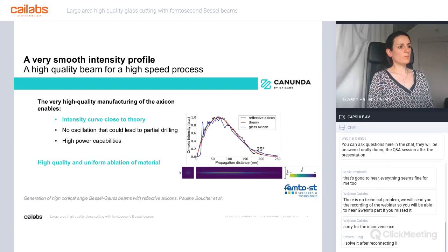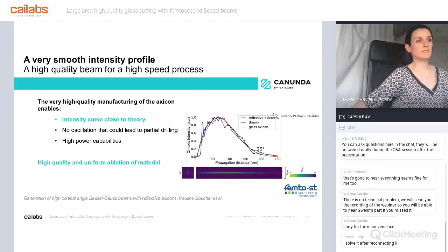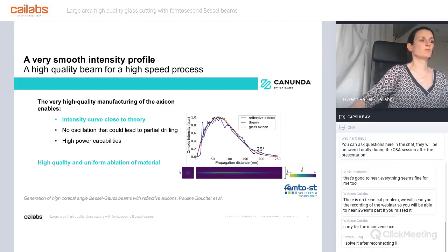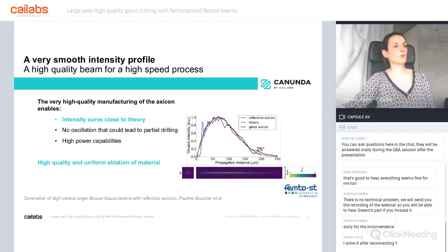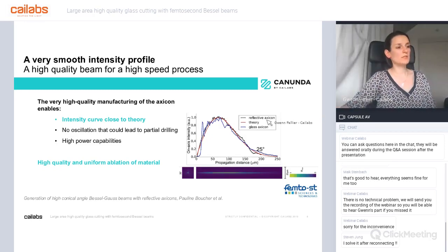The Bessel beams that we have generated with reflective AXICONs are actually the Bessel beams with the best quality that we have found in the literature. You can see that first on this slide: in red you have the theoretical curve of a Bessel beam, and in black you have what you get with our AXICON. It's extremely close to the theoretical curve. In blue, you have what you get with a quite good quality transmissive AXICON, and you have a lot of oscillations, which are pretty bad for the processing, as I just said.